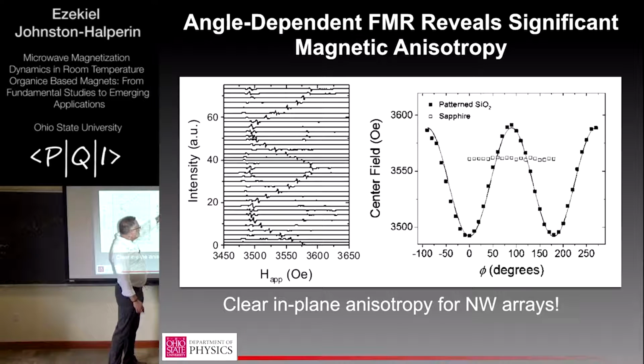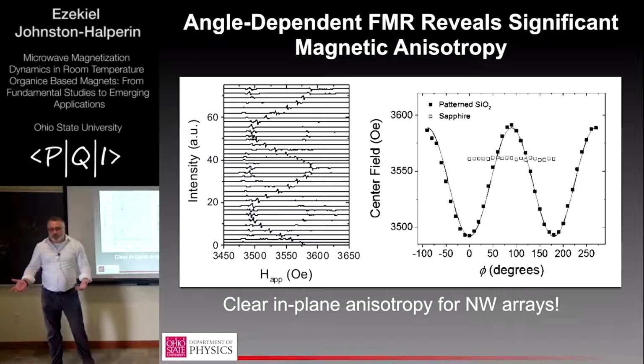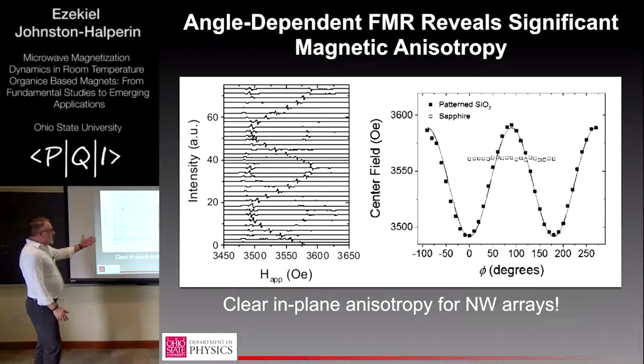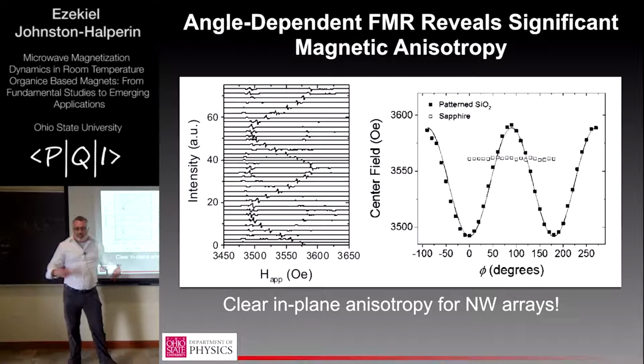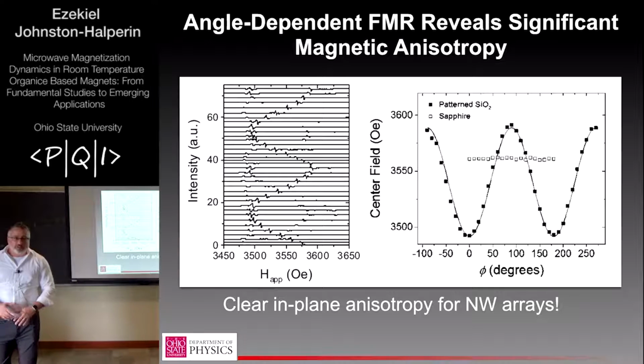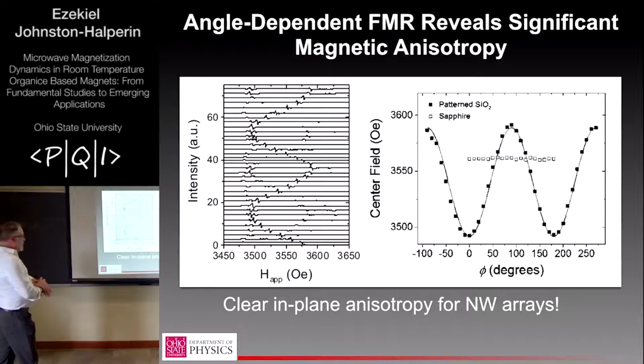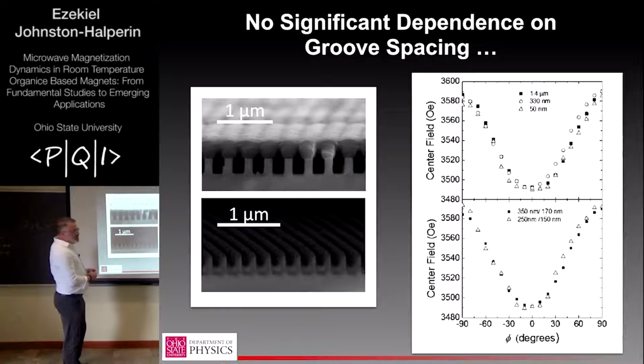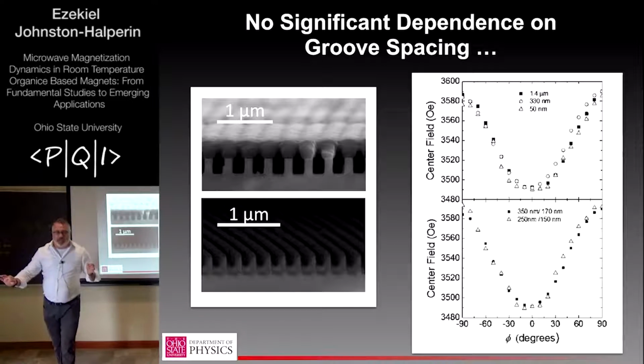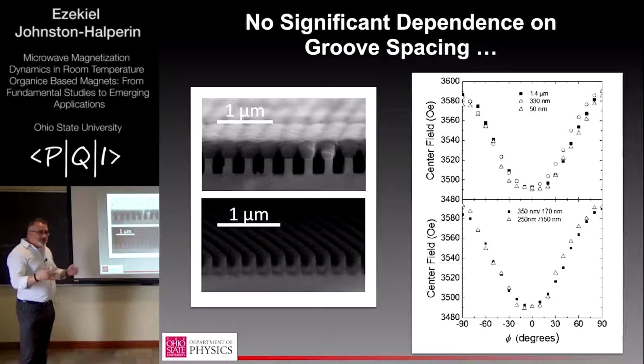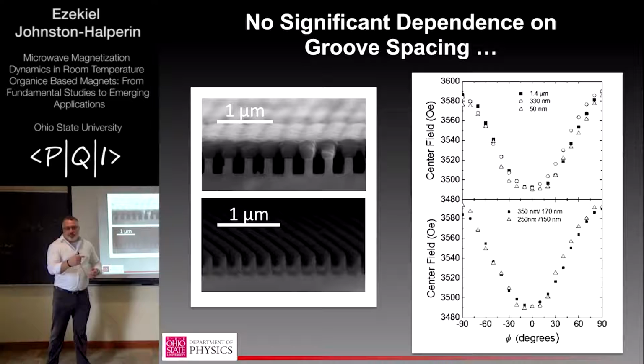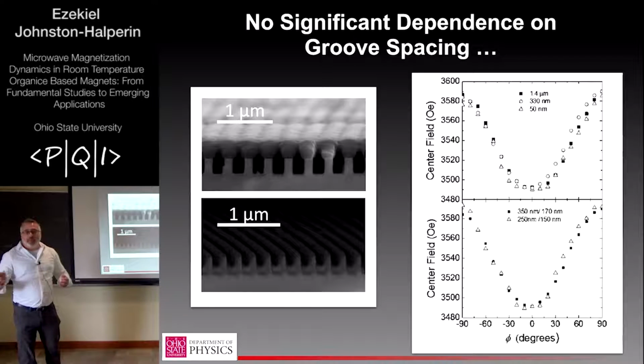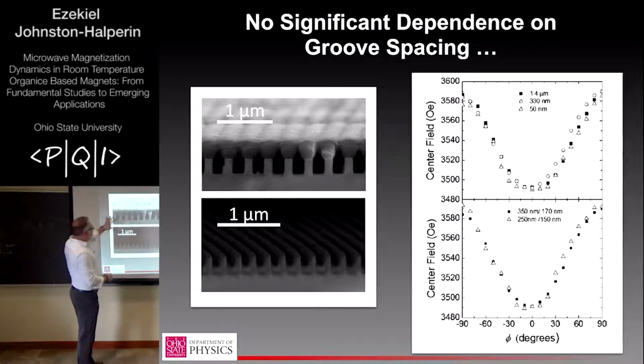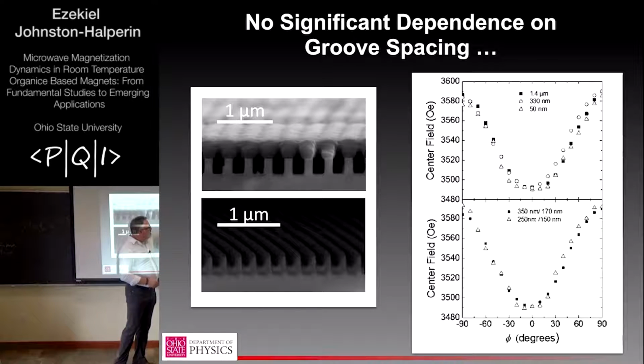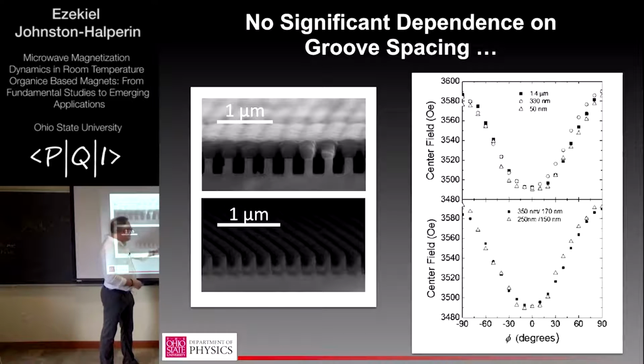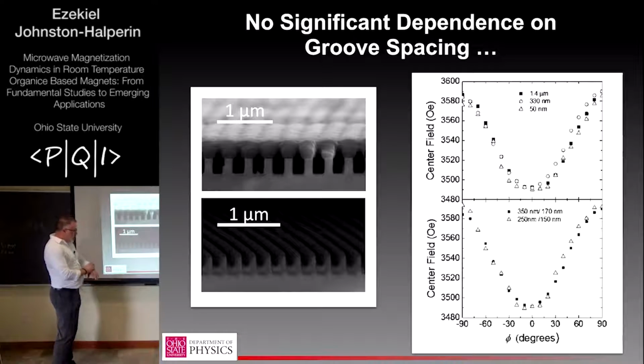This variation in the center field is a measure of the strength of the anisotropy field. And this is comparable to the saturation magnetization. So this is a very large anisotropy for the material. That's not necessarily surprising because you're making wires, and wires are anisotropic, so one might expect, if we do some calculation for shape anisotropy, magnetization perpendicular to the wire should be different from magnetization along the wire. So we tried to test this by doing a thickness dependence, which you can see overlaid here, as well as varying the pitch of the array to vary their overlap.